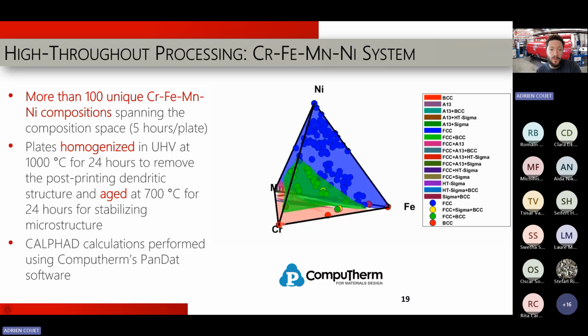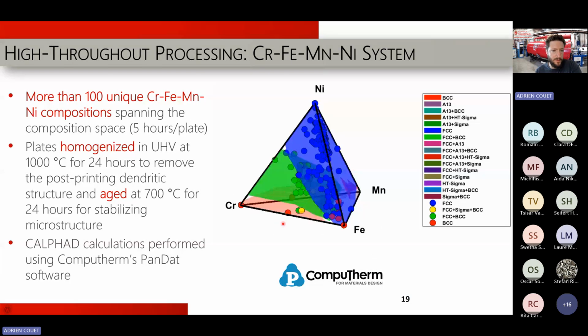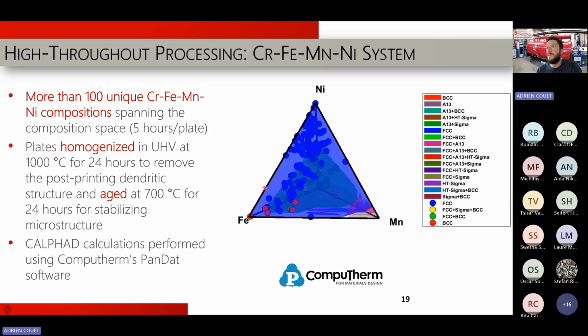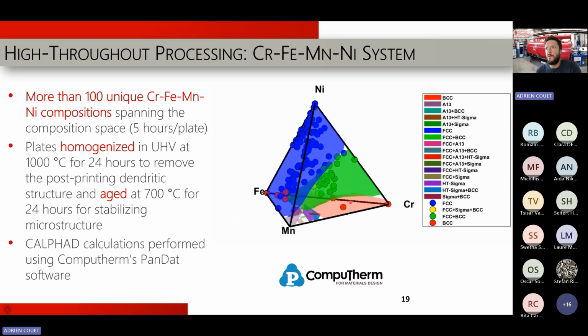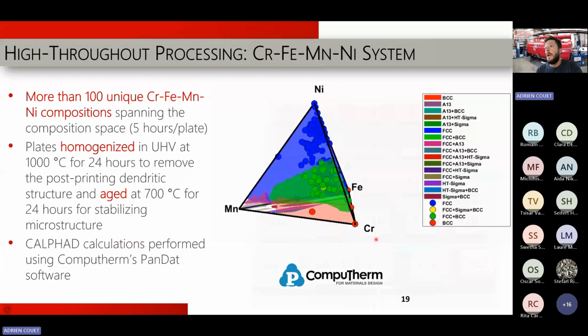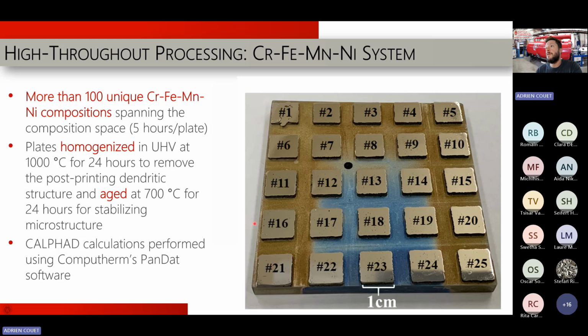You don't see much toward high chromium and high manganese because those parts don't print very well, right? But we have a single phase and also dual phase when you get closer to the chromium-rich area. So here is the look of the plate once it's been polished.